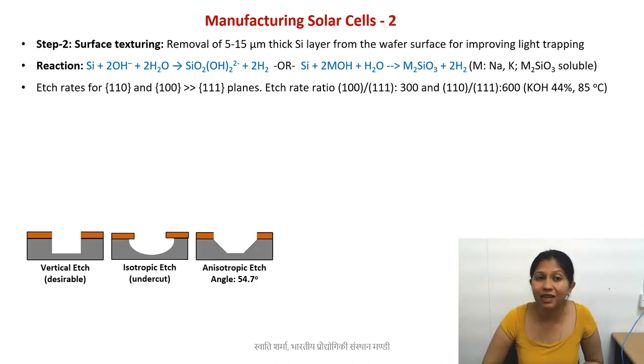In the case of silicon with KOH, you have anisotropic etch with less etching in 111 planes. You get pyramid-shaped structures with some flat plane in the bottom. The angle is always 54.7 degrees, determined by the crystal structure.